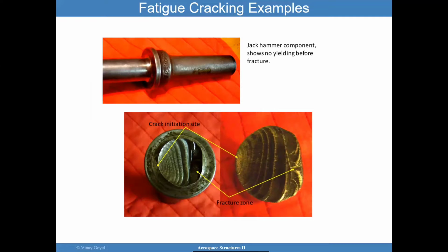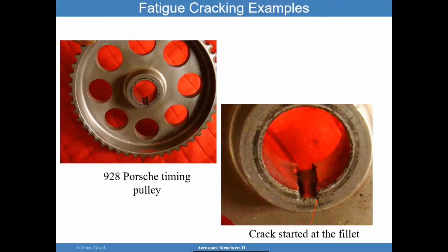Here's an example of a jackhammer component showing no signs of yielding before fracture. It's quite surprising, but yes, you could get fatigue, and the fatigue could occur with no signs of yielding. So that's a very important consideration. You have here a Porsche timing pulley, and in this case, a crack initiated at a fillet. It's a 928 Porsche.